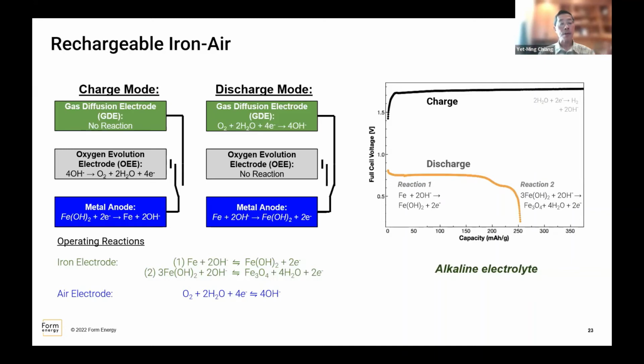So the one for the air electrode, for taking in oxygen, the oxygen reduction process, and making that oxygen available to the iron for oxidation is referred to as the gas diffusion electrode, right? Or the ORR electrode, oxygen reduction electrode. And then there's an oxygen evolution electrode, which is the generation of oxygen gas that leaves the system. And then you have the third electrode, which is the metal anode. You see the reactions down here at the bottom for the iron air case.